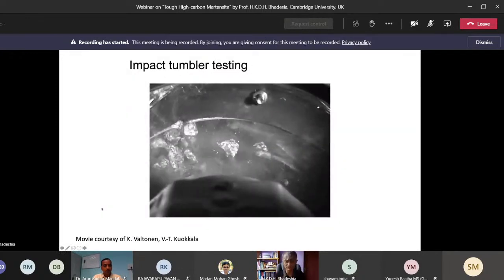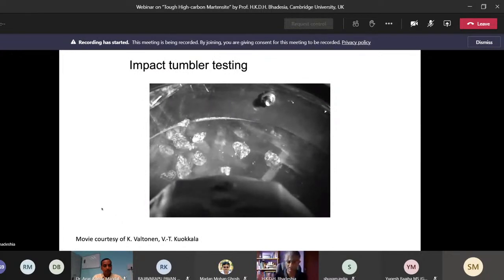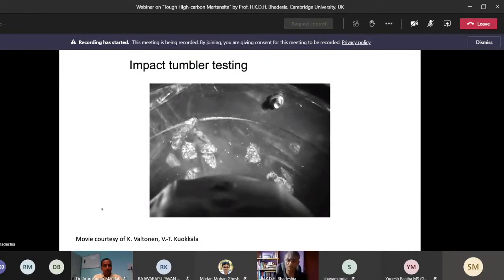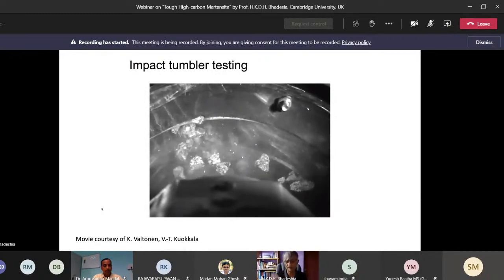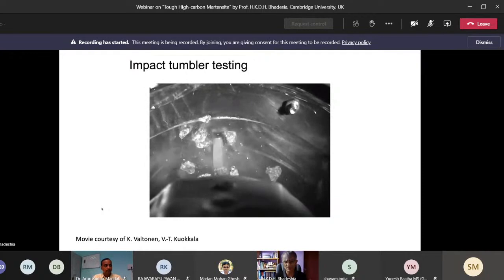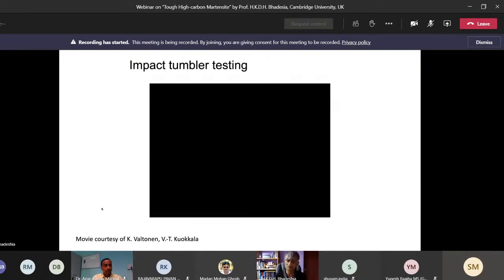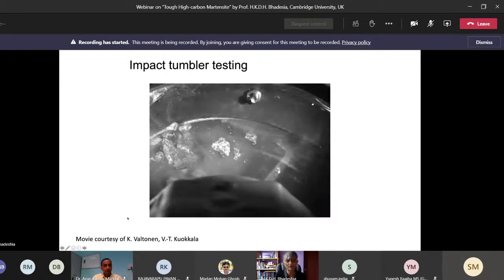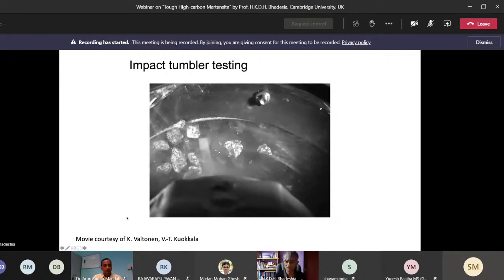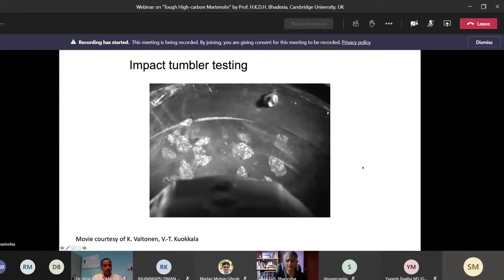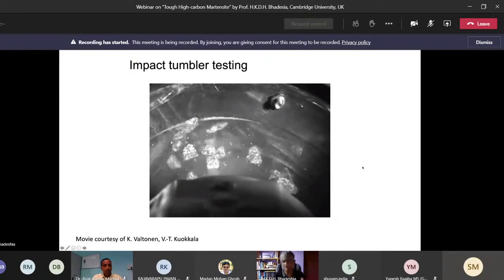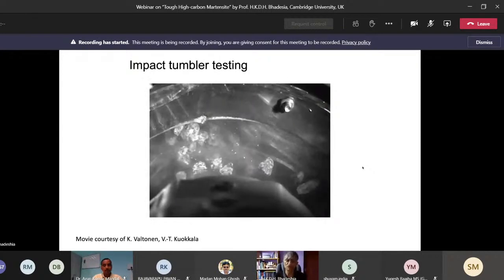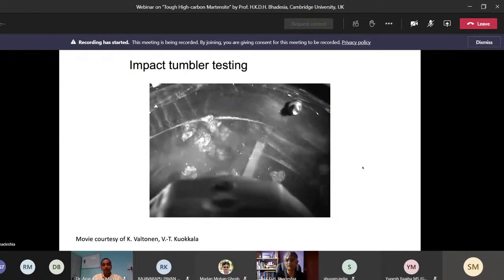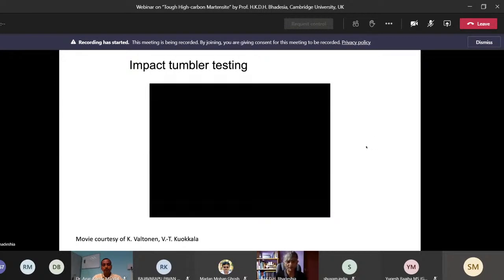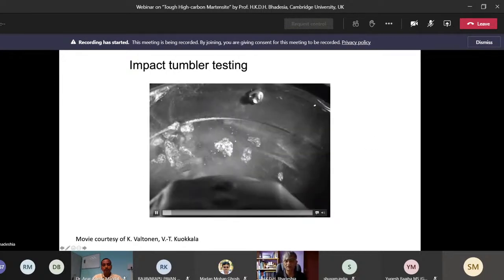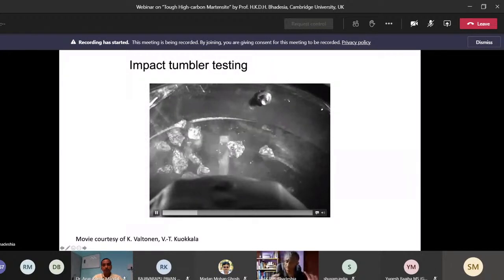Right, now, another experiment that we've done in collaboration with our colleagues in Tampere University in Finland and with Tata Steel is that we subjected this steel to very severe impact and abrasion. So this is our sample here, which is rotating at a very high speed. This is a slowed down movie, all right? So it's 300 revolutions per minute. And it's impacting these granite particles, which are inside this tumbler.